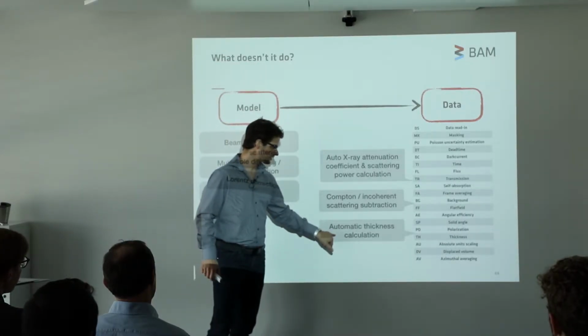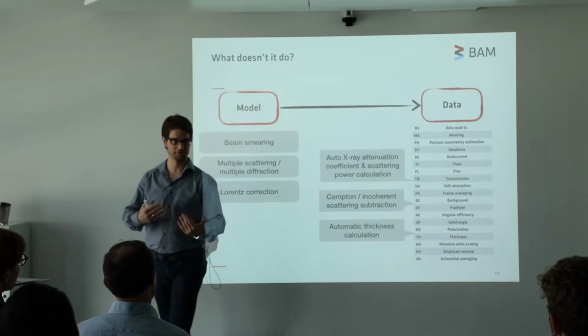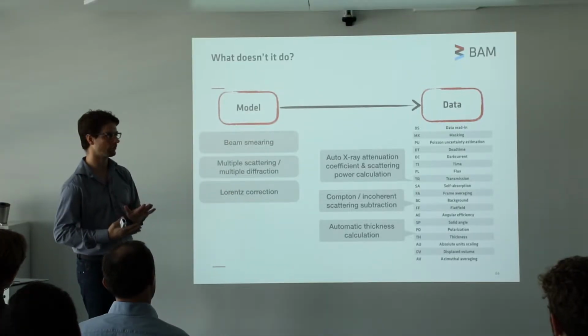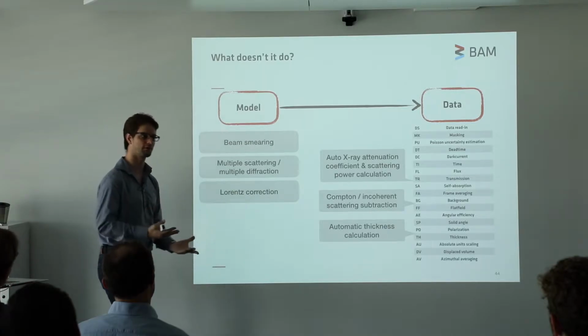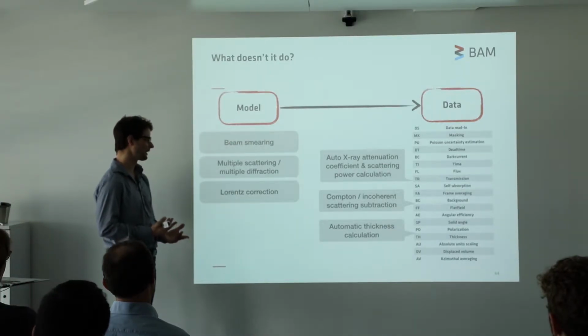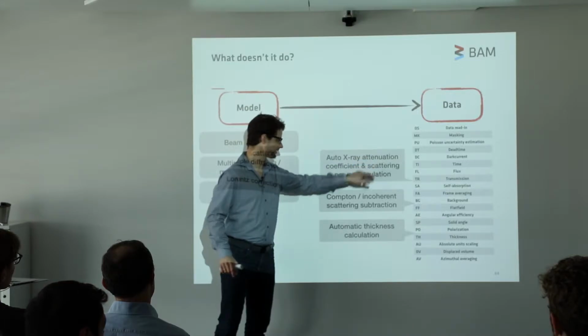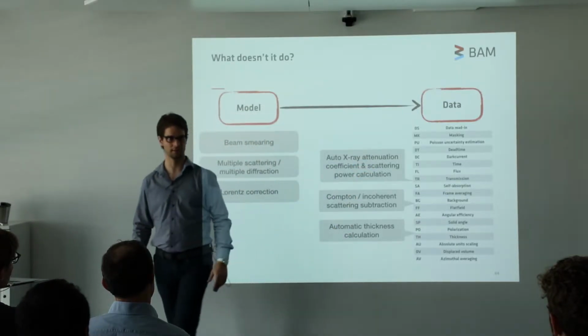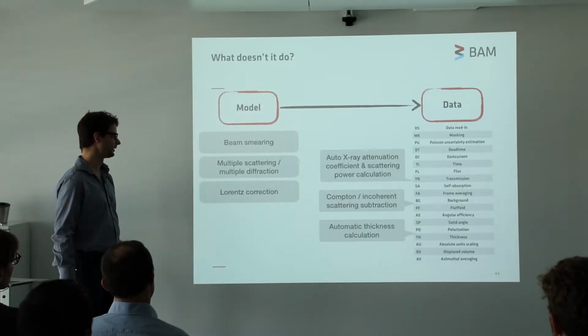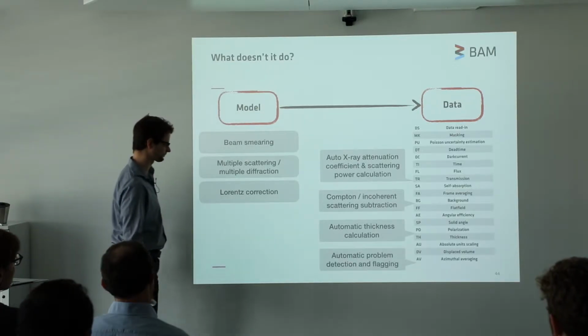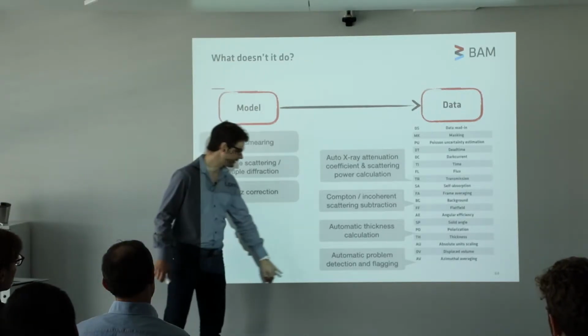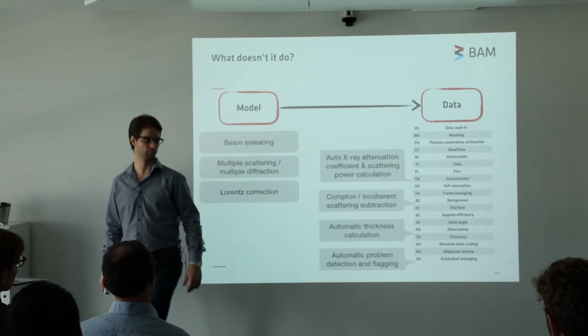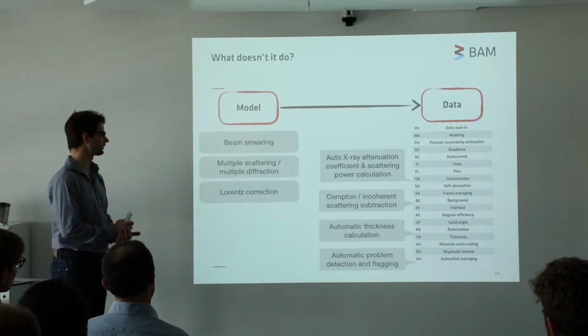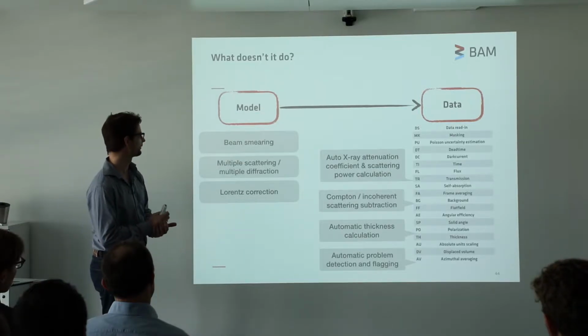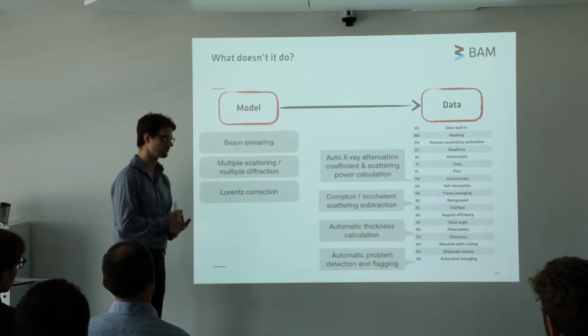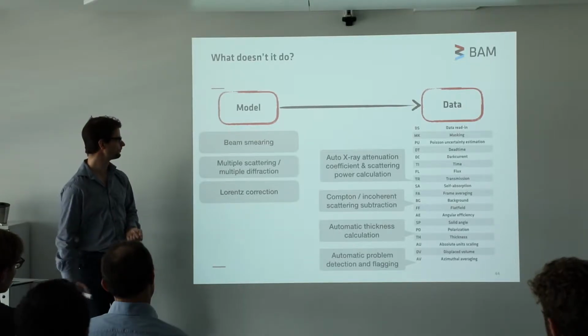We will do an automatic thickness calculation. In particular for powders, this is very important because you don't know how densely you've been able to pack your powders. You don't know how fluffy your particles are. So by knowing the X-ray attenuation coefficient, we can calculate the thickness and correct for this. We've done this by hand, and this works. And we can automatically detect and flag possible problems. This is particularly useful for the users, but also for us, so we can find out if there might be any issues with your data that we need to take into account.